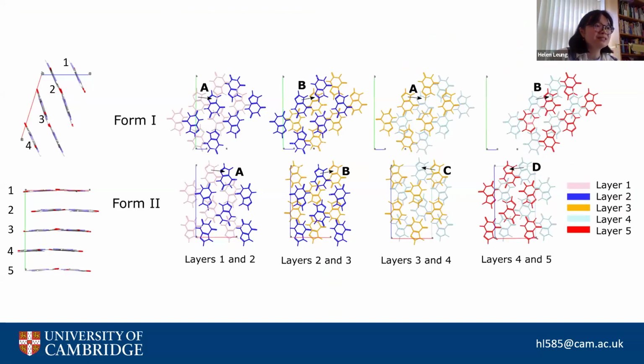Okay, so we tried to model this a bit more by trying to understand what this layer interaction looks like and how these layers are related to each other. So on the left, I've labeled all the layers of xanthine Form 1: 1, 2, 3, 4, and then I've labeled the layers of xanthine Form 2: 1, 2, 3, 4, 5. Just because of the way that the unit cells are defined, they each have 4 layers in one unit cell, but you can't see the 5th layer in Form 1 xanthine in this particular schematic. But we essentially labeled 5 layers from Form 1 and 5 layers from Form 2.